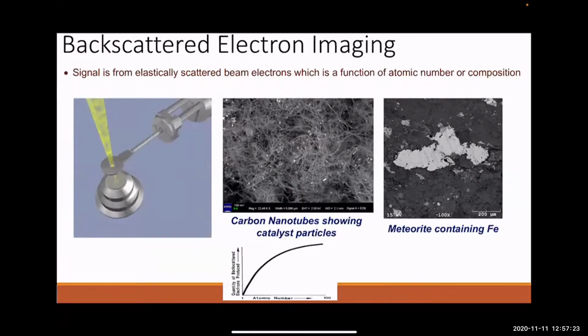Okay, so secondary electrons are good for topography. If you use the backscatter detector, that's good for material contrast. So rather than giving you topography or structure, you'll get more backscattered electrons if you interact with material that's denser. In this case, you've got carbon nanotubes, which you can see as the little ropes here, made out of carbon, which is not very dense. Carbon is a low atomic number, but then you see these bright spots showing up throughout. That tells you those bright spots are something at a higher atomic number, which are the metal catalyst particles used to grow the carbon nanotubes.